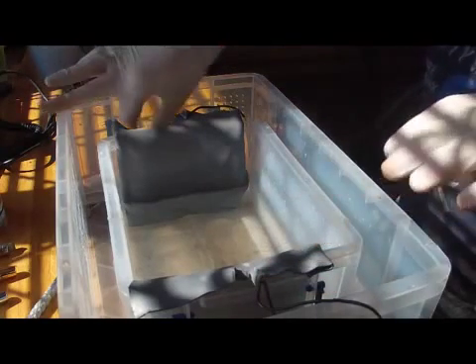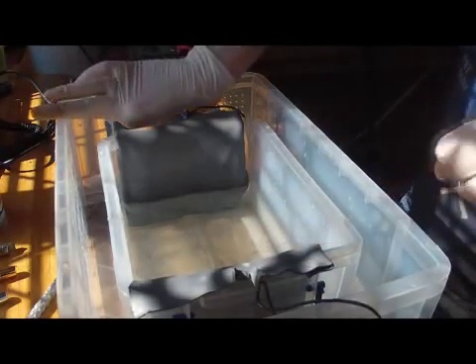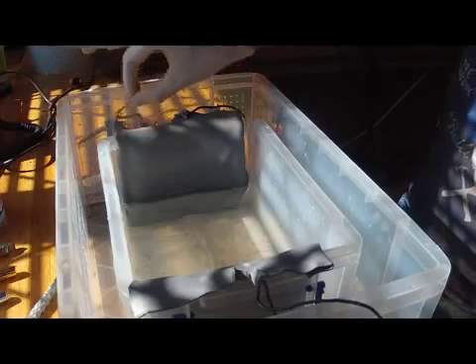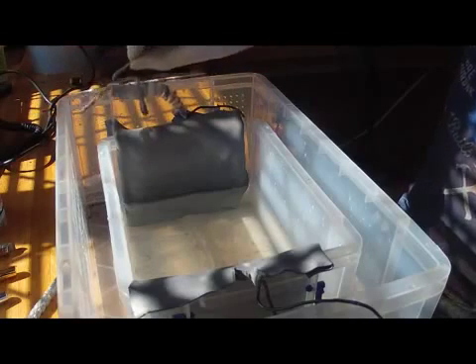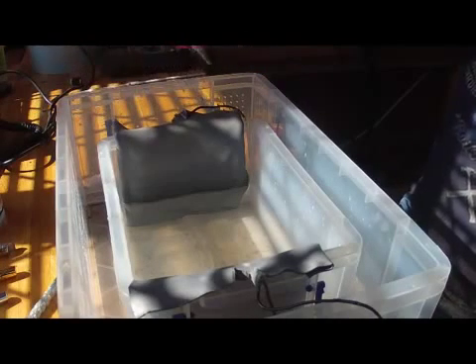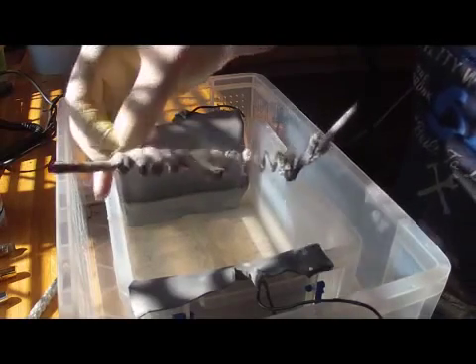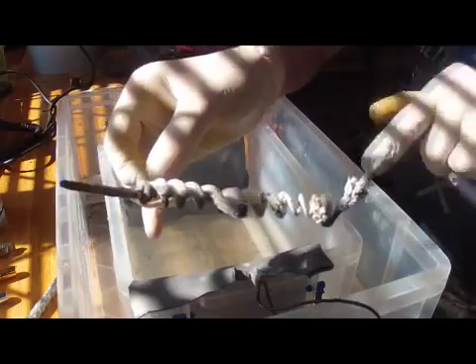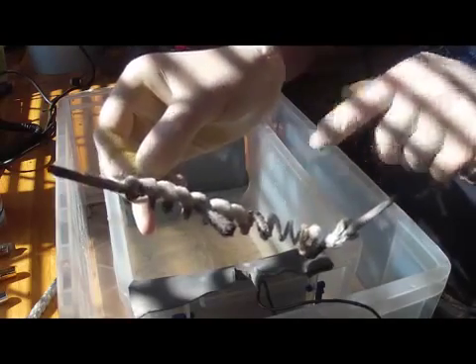What we actually have here is a piece of aluminium welding wire. Now it just goes to show you what other alloys are in there, because it's corroded that much. I'm not going to snap this because it will go everywhere. But this is just brittle. It will just snap into pieces. You can actually see it around the actual coils there, how it's split up by itself and crystallized.